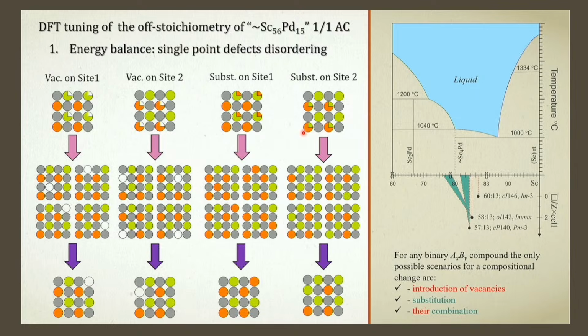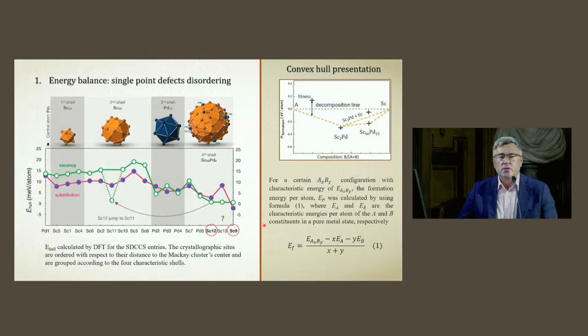But if you wanted to make some irreducible representation and restore some symmetry elements, you will get a reduced subset with ordered models inside. So this works with only one defect introduced into the structure. We did the same with our clusters, testing all the positions inside the structure, introducing only one defect inside.